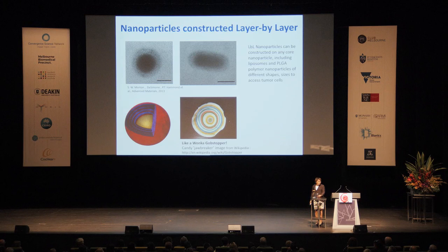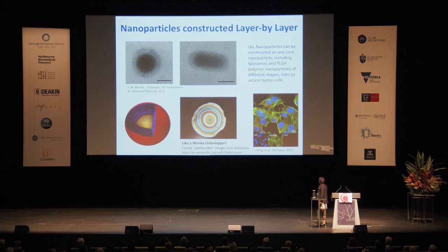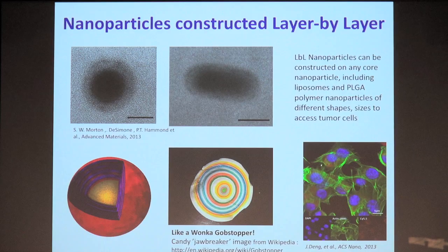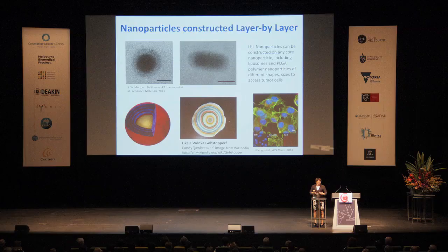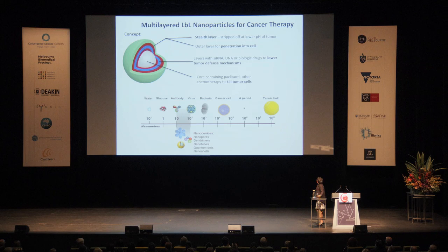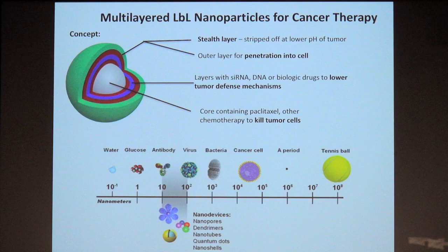And we can design the outer regions of these nanoparticles so that cells that see these particles want to take them up into their interior. And that is how we can deliver drug to these cells. So we are actually using this to address cancer. And it's really a very simple concept. We take a nanoparticle, and the nanoparticles that we use are about 100 nanometers, right around this size, not too far from the size of viruses.